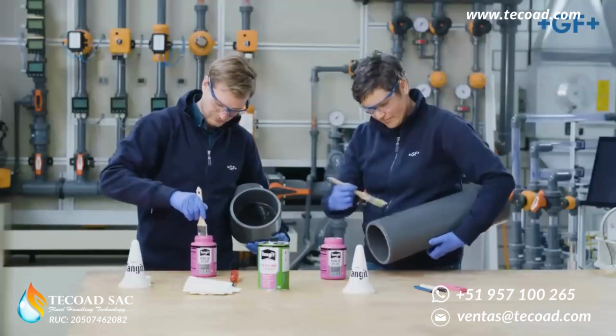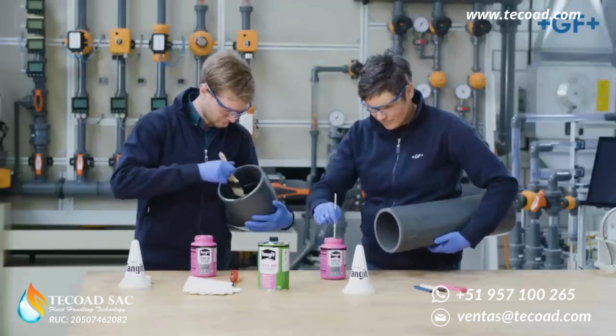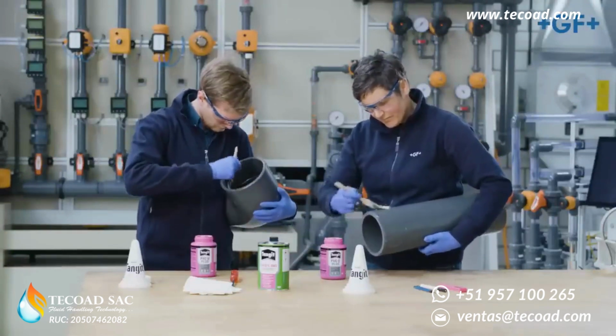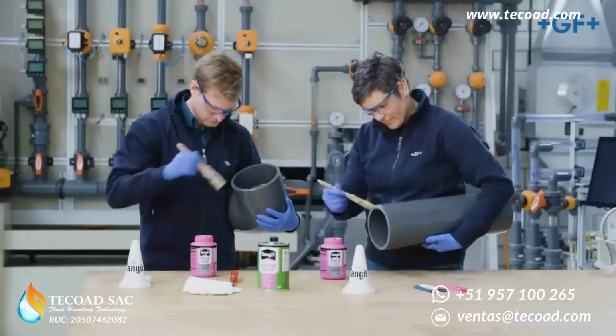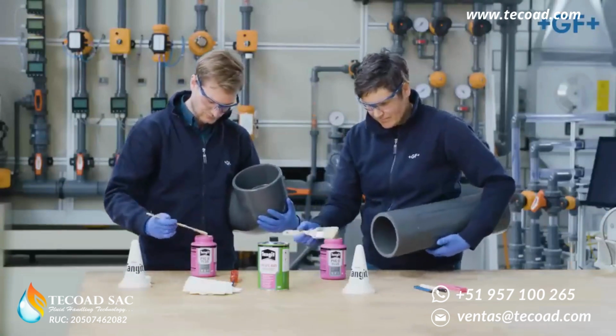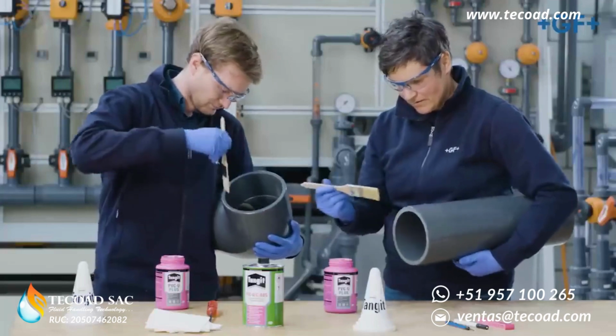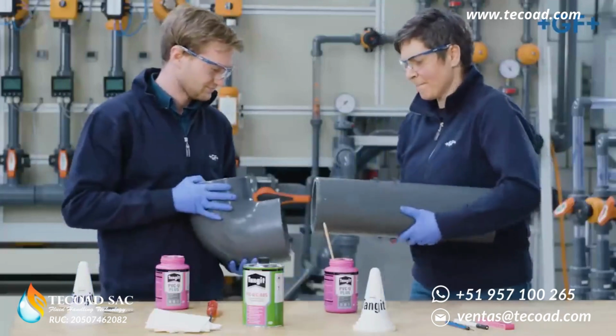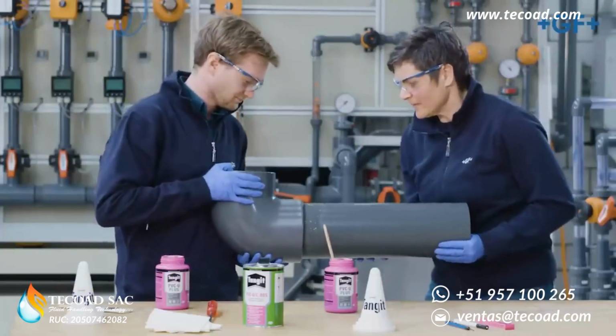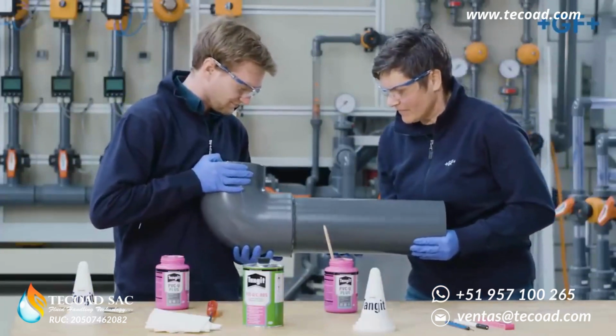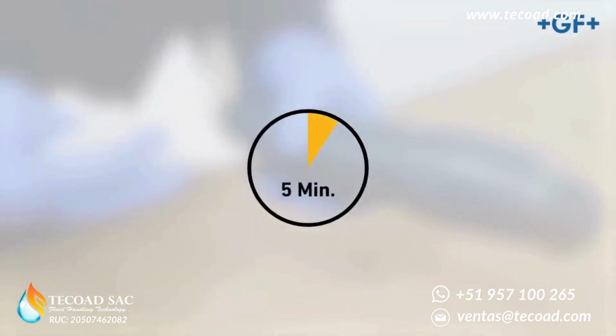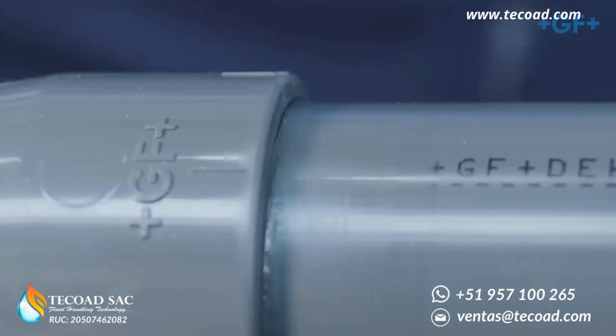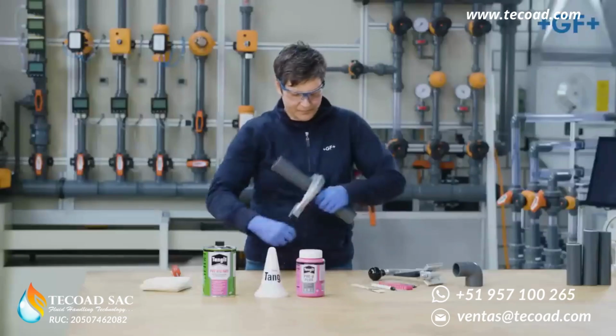Our experience and tests show that pipes with a dimension of about D250 or greater have oval distortions to some extent, which could result in a bonding gap of more than 0.6 millimeters. For this reason, the cementing must be carried out with great care and by several people at once. Never move the pipes during the first 5 minutes after cementing. After this initial period, the joints may be carefully exposed to mechanical stress, thus enabling a continuous workflow.